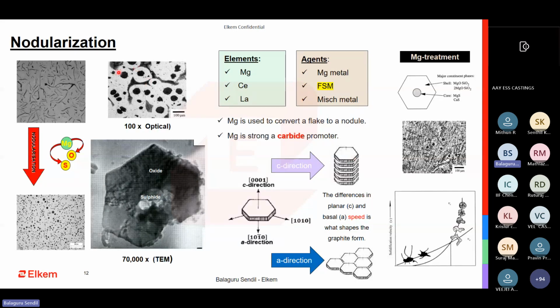You have a very nice optical microstructure here, H1, at 100x. If you magnify further, you always see some sort of sulfide core with a hexagon shell. The hexagon is important because graphite is also a hexagon shape. So when you have a hexagon shape, it can stack one on top of the other, or it can join like this and form a plate. So these are the two growths in which a particular nucleus can grow. This nucleus is always non-metallic, MgS, magnesium sulfide, in the case of ductile iron.